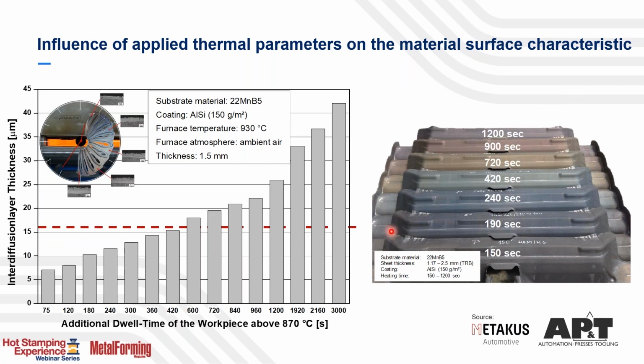In the next, we see a comparison between different dwell times and the effect on the interdiffusion layer coating thickness in the final state or before quenching the part in the hot forming die. Main OEMs are requesting an interdiffusion layer of 16 microns. And what I brought here is the dwell times as soon as you have reached 870 degrees. As soon as you have reached that and you add 75 seconds or 600 seconds or 2000 seconds, it has a very large effect on the growth rate and the final thickness of the interdiffusion layer.